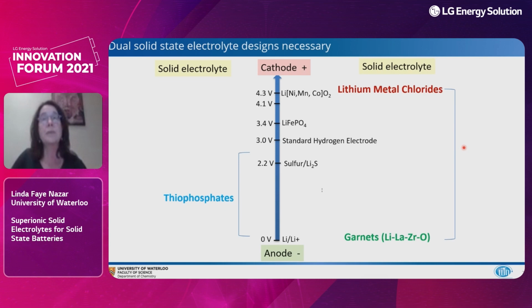So I wanted to say at the outset that there's probably not one magic bullet here, or a silver bullet, or a lithium bullet. Probably dual solid-state electrolyte systems are going to be necessary. So if we think of trying to optimize the cell potential, we're probably going to have to couple something like a garnet with a lithium metal chloride as a solid electrolyte in the cathode, as the catholyte. On the other hand, if we think about lithium sulfur systems, we can probably get away with things like thiophosphates because their voltage range is appropriate for the lithium sulfur cell. But it's pretty hard to imagine any solid-state electrolyte that's really going to fit both ends of the cell, so to speak. So that's just kind of a caveat here.